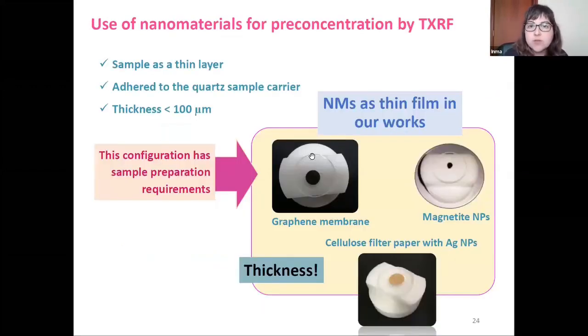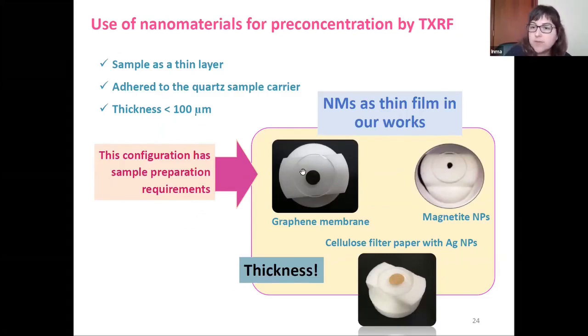Thus, if we use nanomaterials for TXRF, we need to prepare them according to what was mentioned above. It means using a thin layer of nanoparticles, as we can see in the slide, of a lower thickness, and they have to be adhered to the quartz sample carrier, since the analysis with this technique is performed in a vertical position. So we need to fix these nanomaterials.